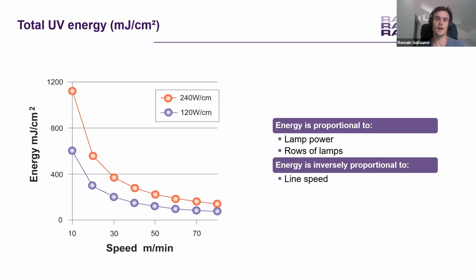Compared to a 2 times more powerful lamp, you reach 2 times more energy, so you get 1000 millijoule per square centimeter. So you have energy proportional to the lamp power, but you also have the energy proportional to the number of lamps, so the row of lamps. That's quite easy to imagine. If you put 2 lamps next to each other, you will allow the coating to receive 2 times more photons, and so 2 times more energy.